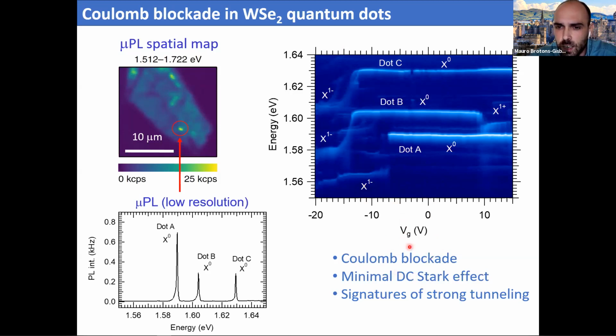First one is that we observed no Stark effect. That means that the permanent dipole of this quantum dot is in plane, and therefore it was not sensing the electric field. And also, there are some signatures, for example this continuous transition, that suggest that we have a strong tunnel coupling. So we wanted to investigate this in a bit more detail.